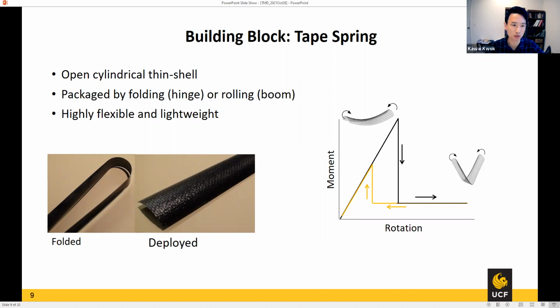So just a little bit about the fundamental principles, so we understand how this works. Basically the mechanical principle behind this is a snapping instability. If you take a tape spring, you will notice that if you bend it, suddenly it goes from uniform bending into a local buckling. And once you get into local buckling, the buckle stays with the same radius. It doesn't change anymore. It can move around, but it is a localized buckle. If you take a look at the moment rotation diagram of that, basically the behavior is that you have uniform bending and then you snap it, and the load drops significantly, and you have a local buckle.